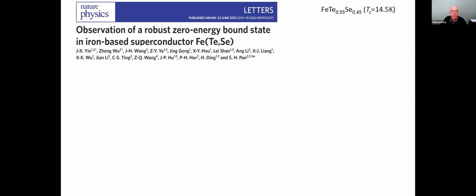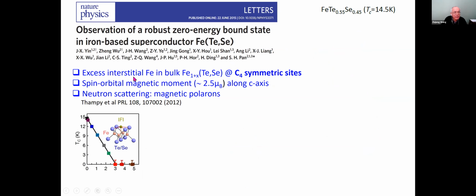But however, the very first observation of a robust zero energy bound state in FeTeSe was actually made on top of excess irons and was actually made about 3 years earlier in 2015. So the excess irons in FeTeSe are very well known. They are as grown. And they sit at the C4 symmetric sites, which is in the middle between 4 tellurium and selenium atoms here. And neutron scattering studied this very carefully early on. The iron carries a spin orbit moment of about 2.5 Bohr magneton and points along the z-axis due to magnetic anisotropy. And they're not ordered, they're disordered.